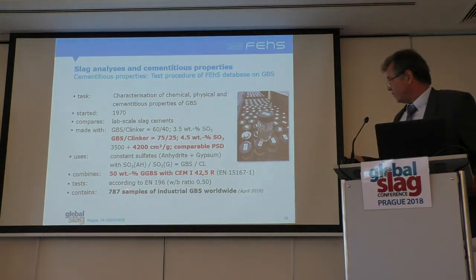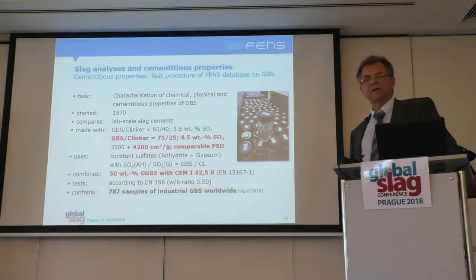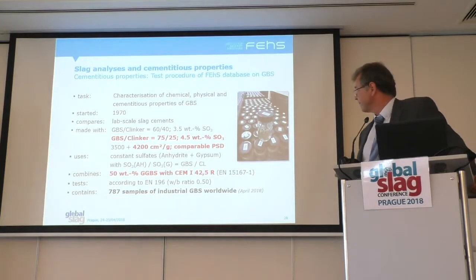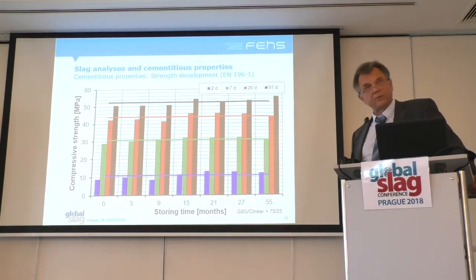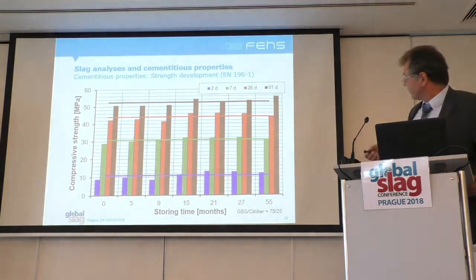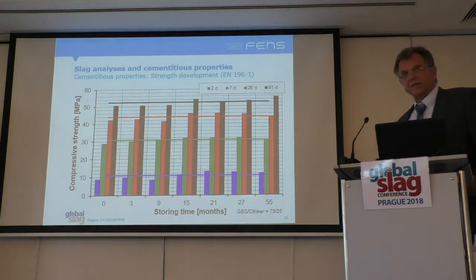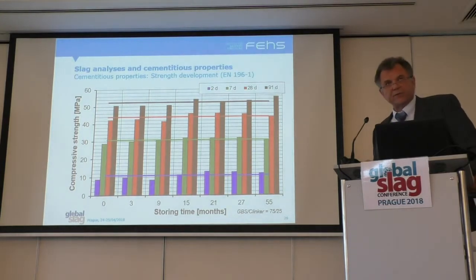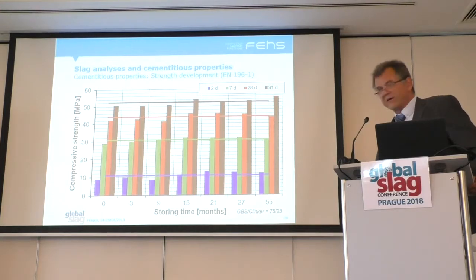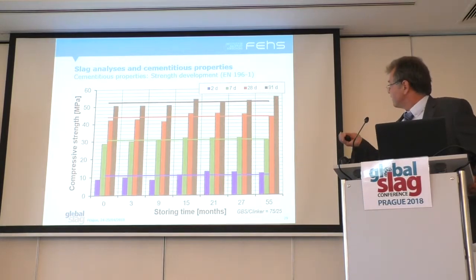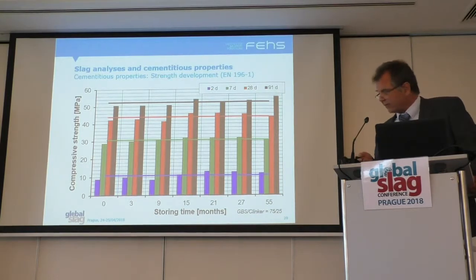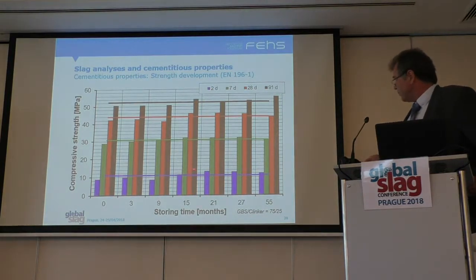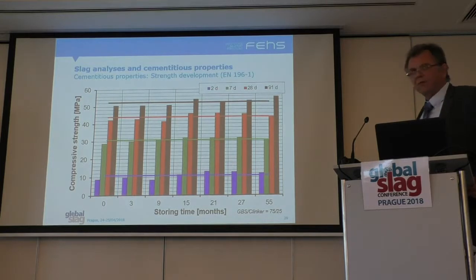In the meantime, we have about 800 samples of industrial GBS coming from all over the world, analyzed according to the same procedure. Also, these samples coming from Delhi. And what you can see here, we made mortar tests according to the European standard, using 75% ground GBS, 25% clinker, and looking to the mortar strength after 2 days, 7 days, 28 days, 91 days. And the lines are the average values, and the individual values are very near around the average.